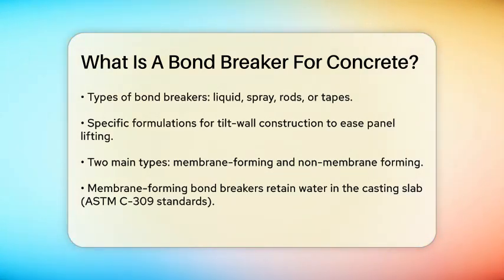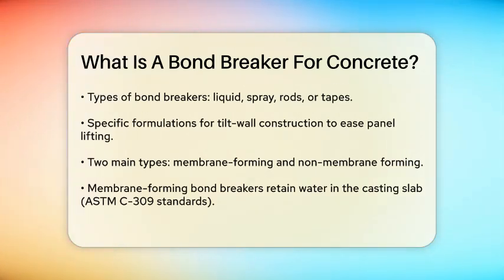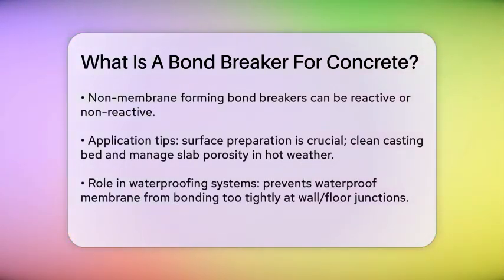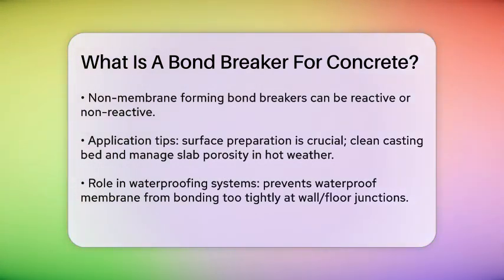When applying bond breakers, surface preparation is key. The casting bed needs to be free of any foreign materials, and in hot weather, the slab must be flooded with water to reduce its porosity before applying the bond breaker. This ensures the bond breaker works effectively and doesn't get over-penetrated into the slab.